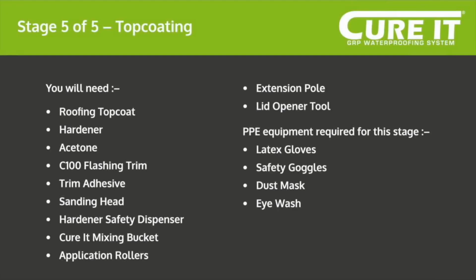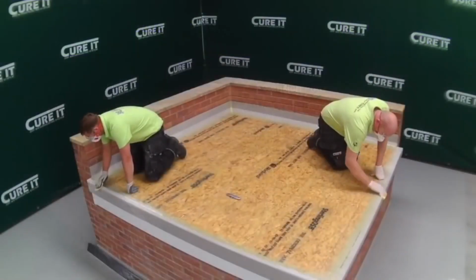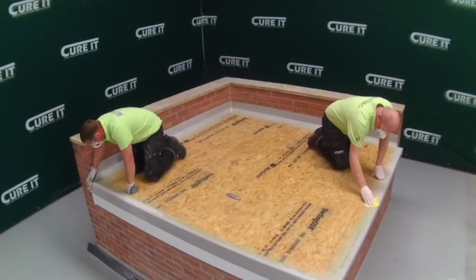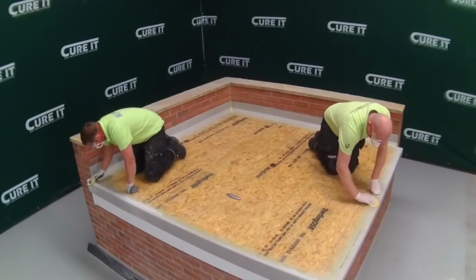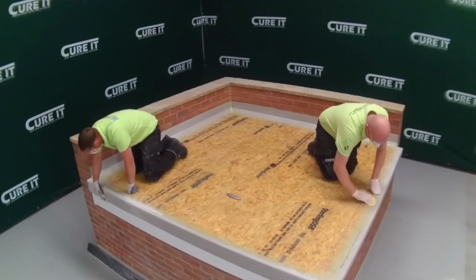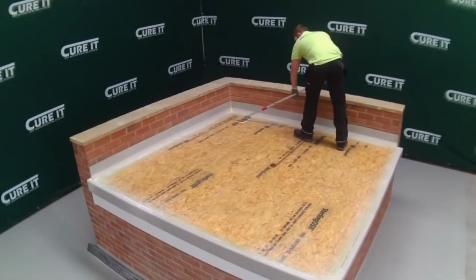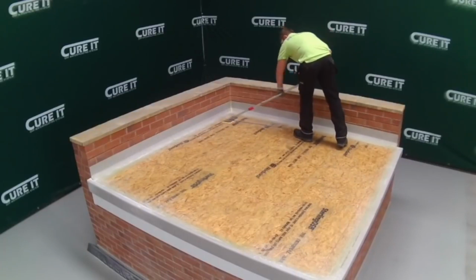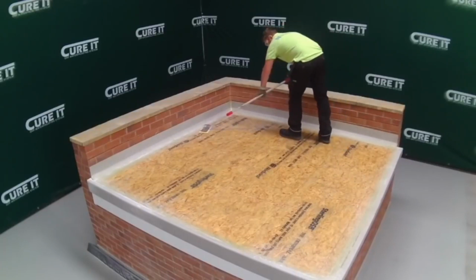The final stage of the installation process is stage 5, top coating. Taking care and paying attention at this stage will produce a roof of superb appearance. To prepare the laminate for the top coating stage, lightly sand the main laminate with a 40 grit sandpaper. You will need to ensure the laminate has cured sufficiently to prevent strands being pulled up while sanding.